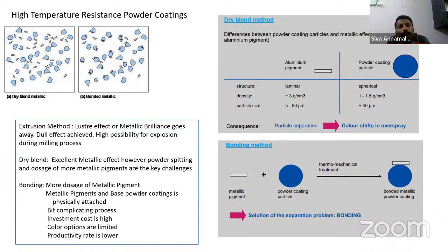So now bonding means, as I said, physically, the pigments and aluminum pigments and base powders are physically attached. But what all we do not know about this bonding, I am going to give a few minutes of information on the points most of us may not know. Number one, the cost of the bonding investment is very high. Even a good quality bonding machine with a capacity of 80 kg per batch will cost you Indian rupees around 70 to 75 lakh landed cost. A good Chinese machine costs $80,000, so landed cost would be 75 lakhs, approximately. Whereas if you go for a European one of the same capacity, 80 kg, maximum 100 kg, it will cost you minimum 1.5 to 2 crore rupees. So the cost of investment is very high, number one.